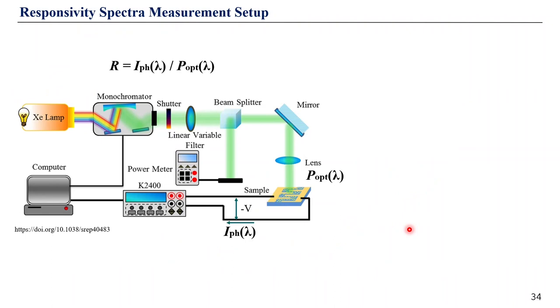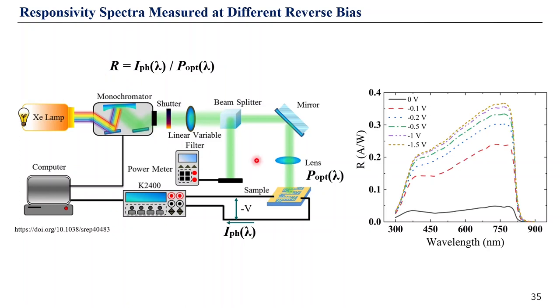So the next parameter which has to be analyzed is spectral responsivity, and it is measured with a similar setup as standard EQE. However, in this case, we need to be sure that it's possible to apply reverse bias because we operate in the photodiode mode. And instead of considering the photon flux and flux of photogenerated charge carriers, as we do for EQE, we deal directly with the power of monochromatic incident light and the generated photocurrent. So the ratio gives us responsivity, or in other words, ampere per watt characteristic, and measuring at different biases gives us a family of curves, which clearly show that the responsivity increases with reverse bias due to increased efficiency of separation of photogenerated charge carriers. And at large reverse bias, we get the maximum responsivity.